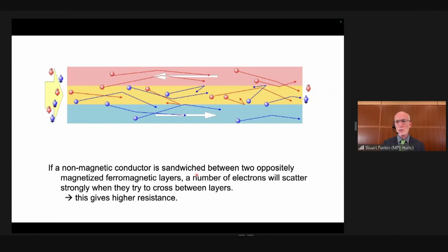However, if we make the copper layer sufficiently thin and the magnetic layers sufficiently thin, then the blue electrons will cross from the lower blue electrode through the copper layer into the red layer, where they will be scattered, and the scattering rate will be stronger because they're now in a material in which the blue electrons are strongly scattered. And vice versa, the red electrons from the top layer can pass through the copper layer into the blue layer, and then they will be strongly scattered. So in this configuration of the two magnetic layers in this sandwich, the electrons introduced from the left-hand side will be scattered strongly everywhere, somewhere in this structure.